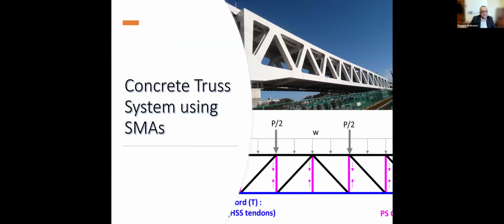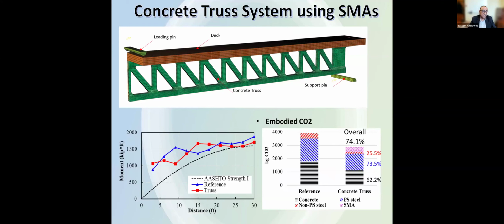So we wanted to try something that's very simple, a simple optimization process, which in the simplest form of that optimized shape would be a truss. So we performed some analysis on trusses. And yes, trusses are more popular in steel than concrete for obvious reasons, simply because tensile members in trusses would have to crack if they're made of concrete unless you pre-stress them, right? And pre-stressing each and every single one of them is a complex process. For example, in a truss like I'm showing here, the verticals are subjected to tension, so you would have to pre-stress each one of them. With thermal pre-stressing, that's possible. So we conducted this theoretical experiment, if you will, on a truss like this with only SMA placed in the verticals.